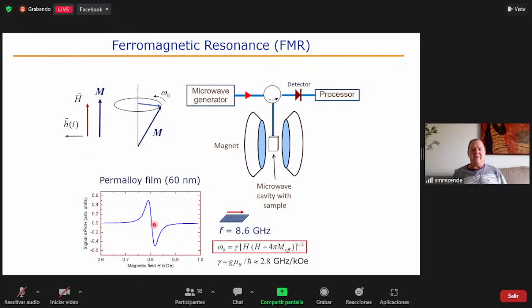And there is a natural frequency here, which is the resonance frequency. So when the driving field has the frequency of the natural frequency, we have a resonance. Since we normally observe this by modulating the magnetic field, what we see is the derivative of the absorption peak. The absorption peak is nearly a Lorentzian, and here is a Lorentzian derivative. This is the ferromagnetic resonance spectrum of a simple permalloy thin film.